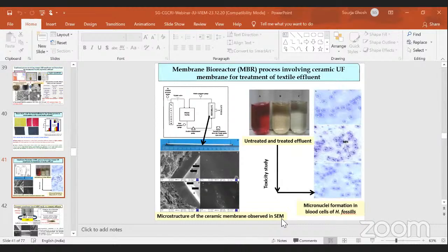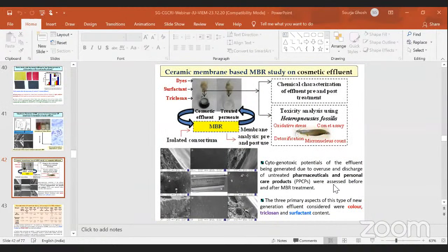Now the membrane bioreactor process was developed based on the ceramic ultrafiltration membrane for treatment of textile effluent. So this is the microstructure of the ultrafiltration membrane used in the study. This is the untreated textile effluent and this is the ambient treated textile effluent. The toxicity of the treated effluent was studied using a fish living system, and the study indicated no significant toxicity was observed on the application of the treated water.